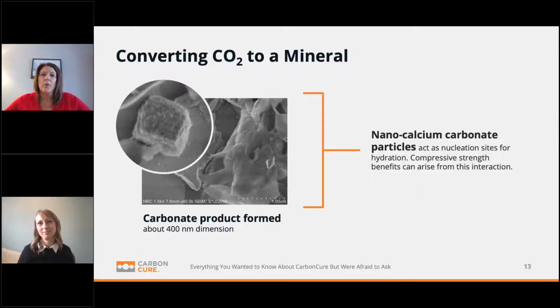But where the real value comes in, and kind of the key to all this, is when these calcium carbonate molecules are created chemically inside this concrete mix, they're very small. They're nano-sized particles that will bind to the outside of the cement grain, thereby increasing the surface area, and we're making the cement more efficient.